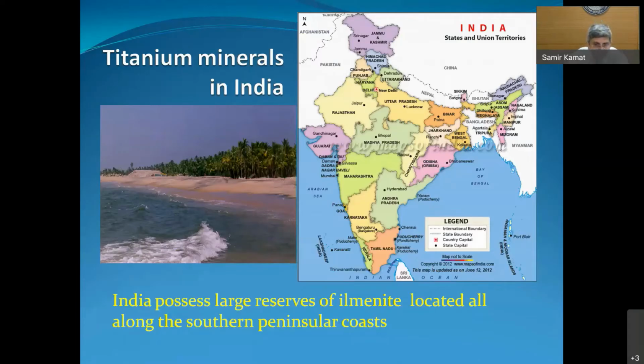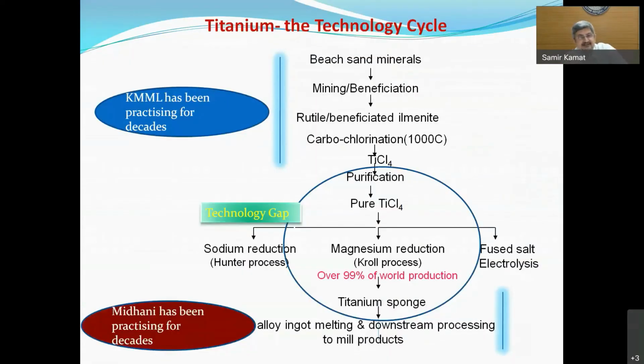India has a very long coastline, and all along the southern peninsular coastline, we have large reserves of ilmenite, which is a titanium containing mineral in the beach sands. Now, if you look at the titanium technology cycle from the beach sands, you have to basically mine the beach sands, then beneficiate it, separate out the ilmenite, and then do carbon chlorination to get titanium tetrachloride, then purify the titanium tetrachloride, and then using either sodium reduction, magnesium reduction, or fused salt electrolysis, make titanium sponge, and then use this titanium sponge and add different alloying elements to make the different titanium alloys which are required for the aero engine program or the airframes.